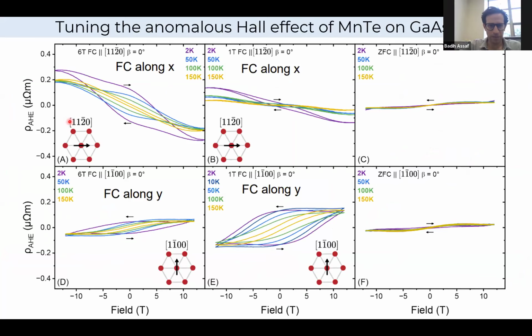So let me reiterate something here. What we've looked at is field cooling along these directions. But I don't know for sure, and it's not easy to figure out if the Néel vector is oriented along 1, 1, 2 bar, 0 or 1, 1 bar, 0, 0. The anomalous Hall effect is only allowed if the Néel vector is along 1, 1 bar, 0, 0. It's forbidden if it's along this direction.